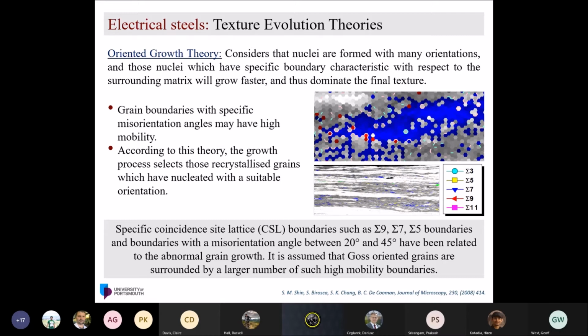For example, we captured that growth grain at a nanoscale, where you'll see some pixels of EBSD. And in fact, from our side, we couldn't verify that theory, and it didn't help us to understand the abnormal grain growth at that stage.